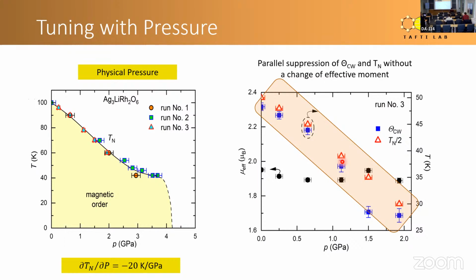So the fact that the Heisenberg coupling is going down is a promising observation, in the sense that you would hope that the ratio of Heisenberg to Kitaev interaction goes down, or the other way around, the ratio of Kitaev to Heisenberg goes up, which is what we really like to have.